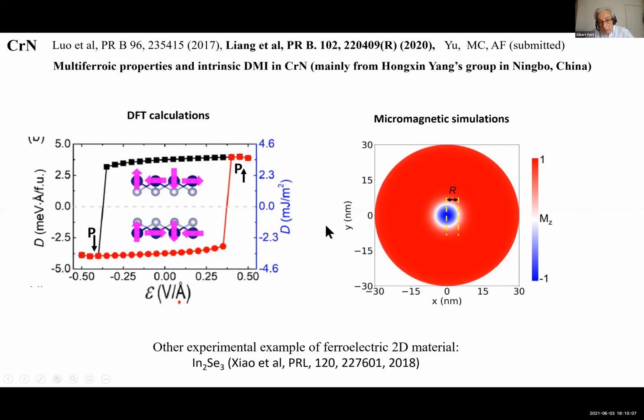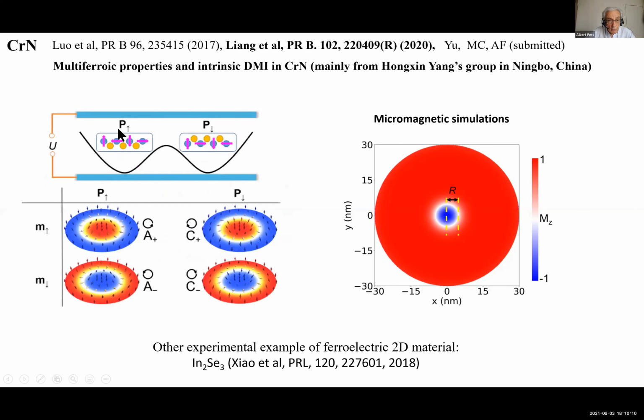This corresponds to this scheme: depending on the electric polarization, we can have skyrmions with different chirality, corresponding to rotation in different directions. And if you also manipulate the polarization, you can have four states with two different chiralities and two different polarizations at the center of the skyrmions. So this opens an interesting way for the application of skyrmions. It has already been evoked in several projects of a device.